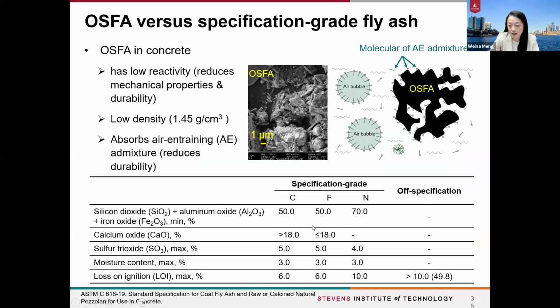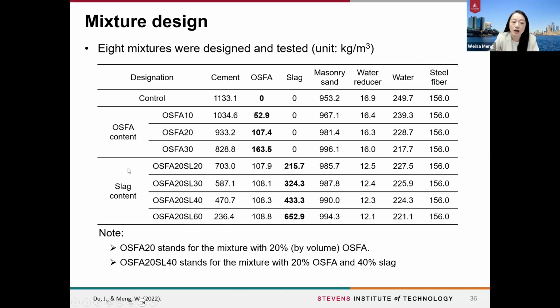compared with the normal fly ash, it has negligible reactive oxides in the system. So the majority content is carbon, and that will reduce the mechanical properties as well as the durability of concrete. Also, the OSFA has very low density. And due to the high surface area of the OSFA, it absorbs some chemical admixtures and some ions. Specifically, it's reported that it absorbed the air entraining admixtures, which could reduce the freeze and thaw durability. So there are a lot of problems for the OSFA.